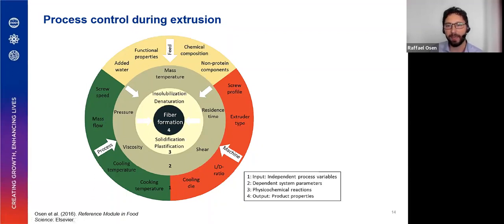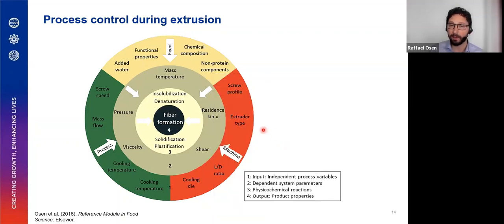Now, all of these independent process variables that can be adjusted, they affect the dependent system parameters during the extrusion, such as residence time, pressure, viscosity, shear, and all of these have an impact on the physical chemical reactions that are happening both in the extruder as well as the cooling die, which then affect the fiber formation. So this is to show really that changing one of these parameters has an effect on the rest of the process, and therefore this leads to many times trial and error approaches during product development.